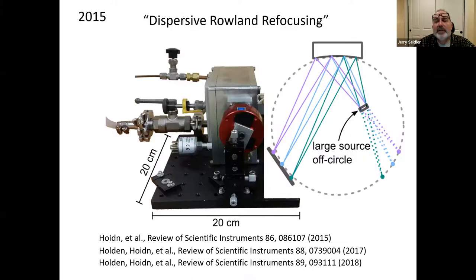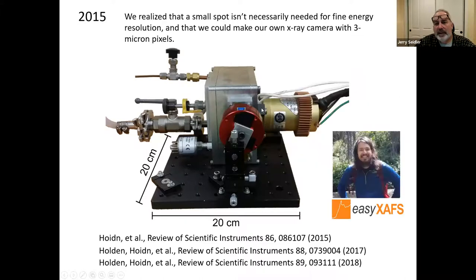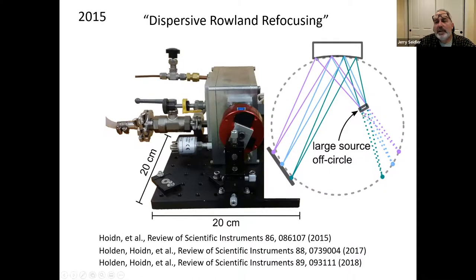And what's going on inside here is there's a small cylindrically curved analyzer and the X-ray tube that's, again, right here, is shining and making a large spot on a sample that's well inside the Rowland circle. And when you do the ray tracing, you find that you have a good averaging over the surface of the sample into different collection cones, striking the crystal on the Rowland circle, and then refocusing here on our X-ray camera, this red instrument here. And so it's a dispersive instrument that doesn't require a small spot size, but still does average over sample inhomogeneities. So it's quite a nice thing Will came up with.